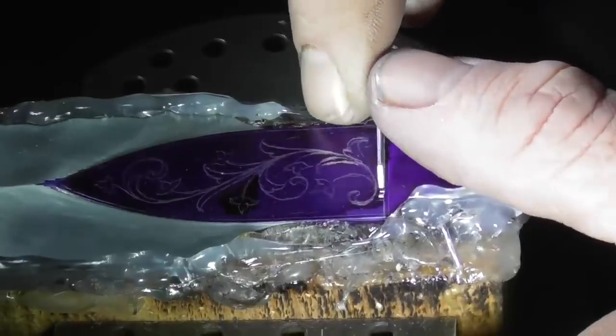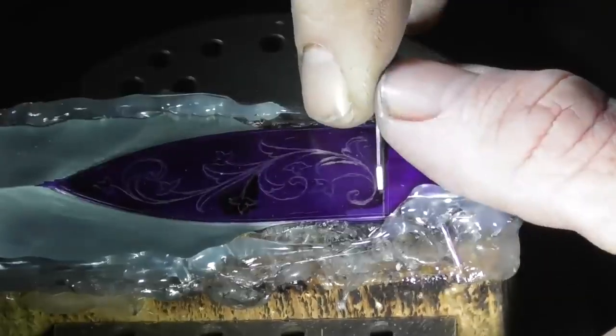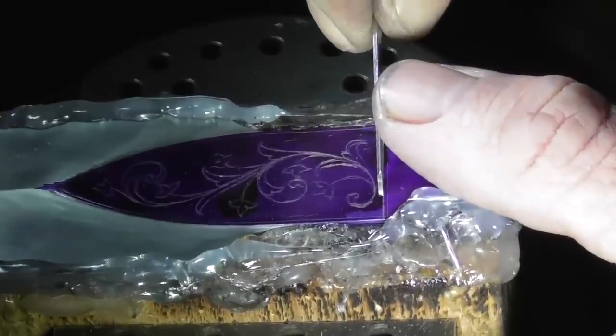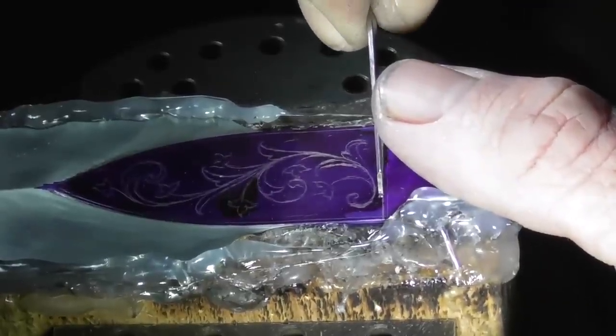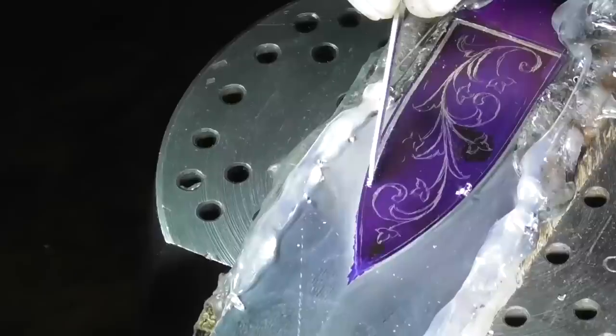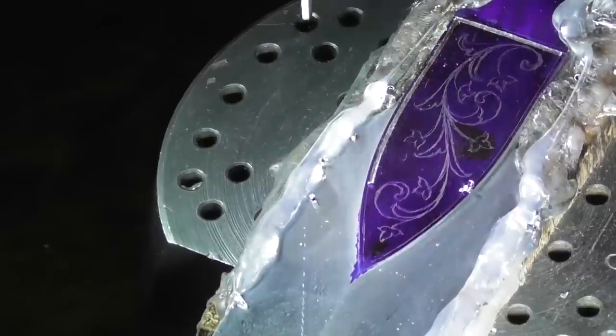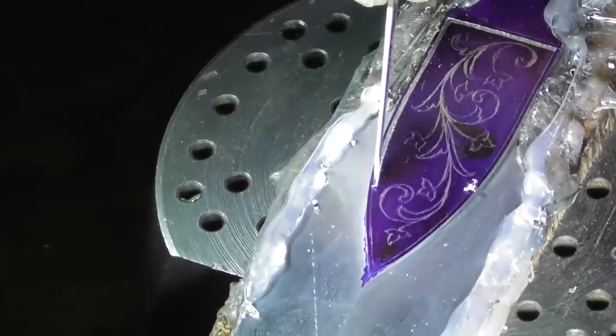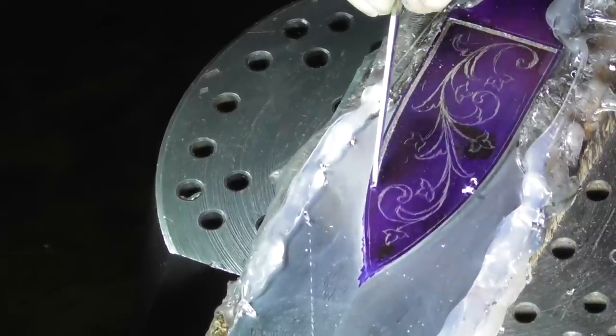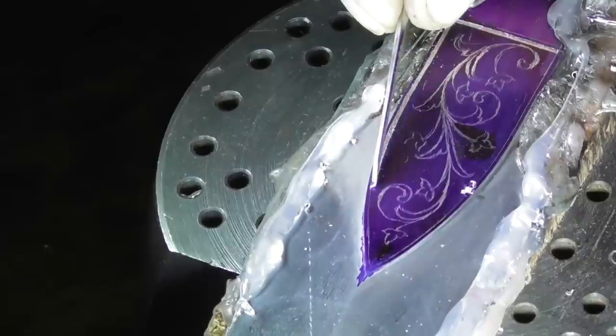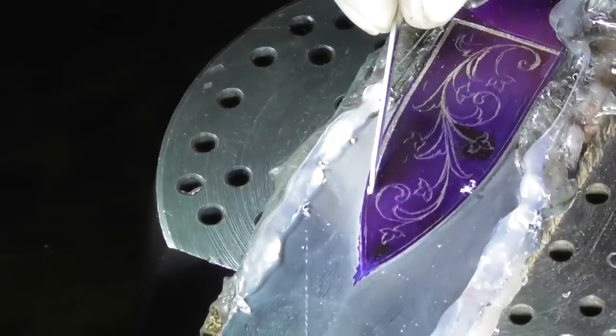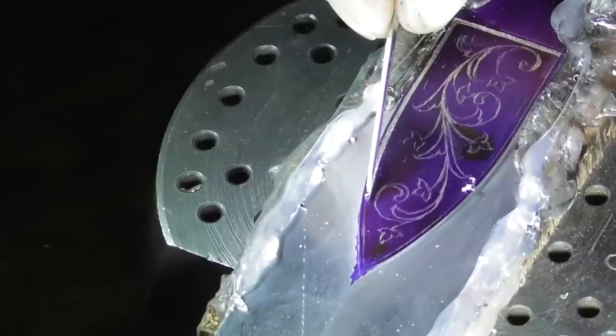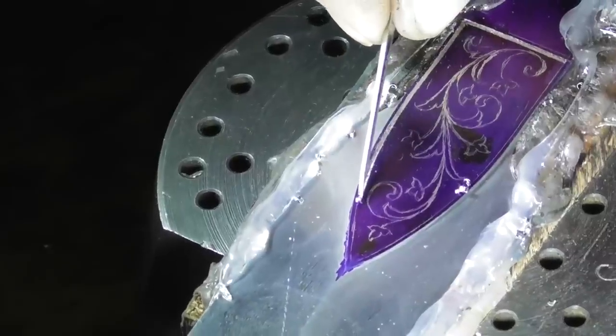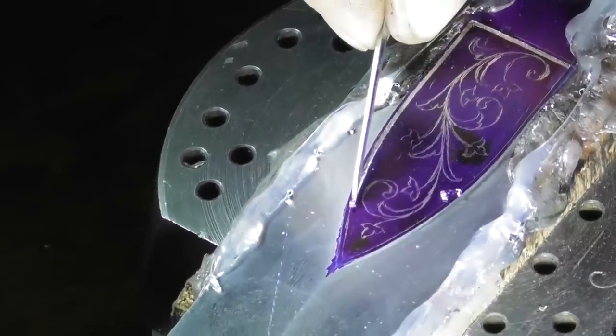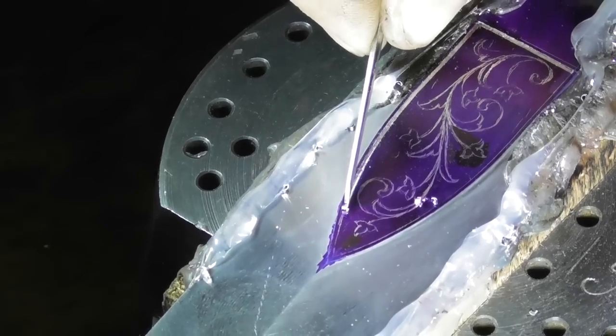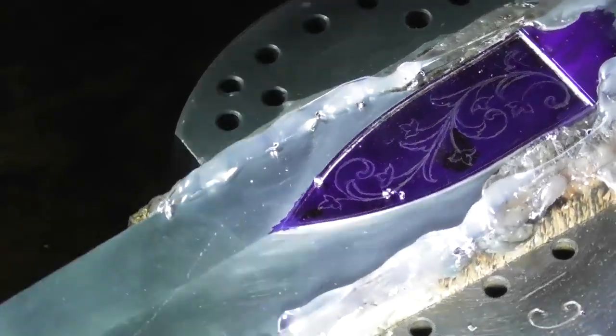Once I have that layout established, then it's time to cut the grooves. So here you see me cutting the channels around the border. The border is going to be gold inlay, and then the overlay is going to be the scroll portion. So with the inlay channels, they need to be a little bit deeper, well, actually quite a bit deeper than the overlay channels, because you want to make sure that they're deep enough that when you sand them flat, there isn't going to be any gold that is going to come out.